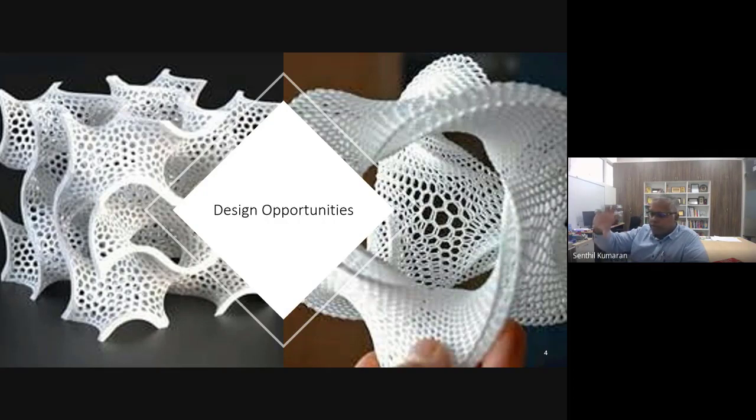Our scaffold was 50 mm by 50 mm by 50 mm, grown in the lab and then tested over time. We did temporal and spatial analysis of the loss of material over time. Spatial matters because you need to know where the absorption and diffusion of water and nutrients into the cells happen. That's why we make surface-connected porous structures, which help transport the nutrients very quickly.